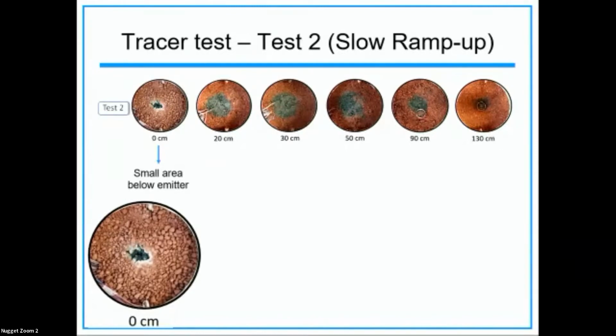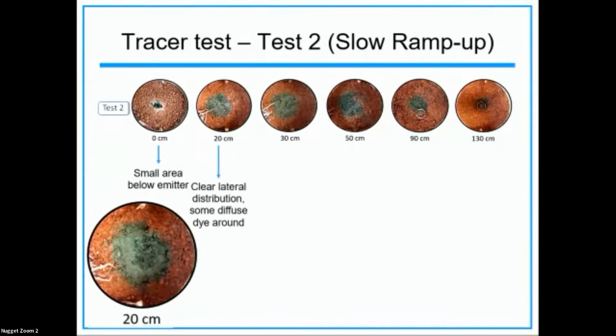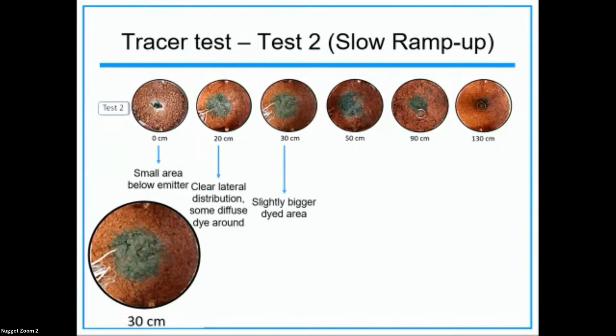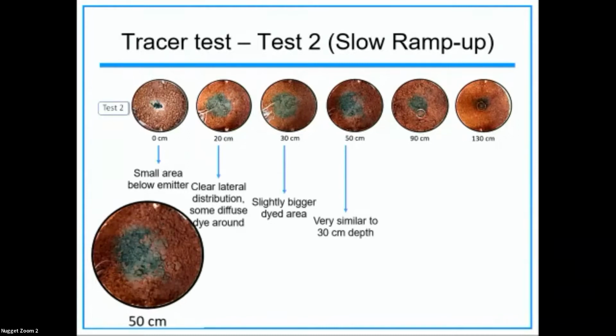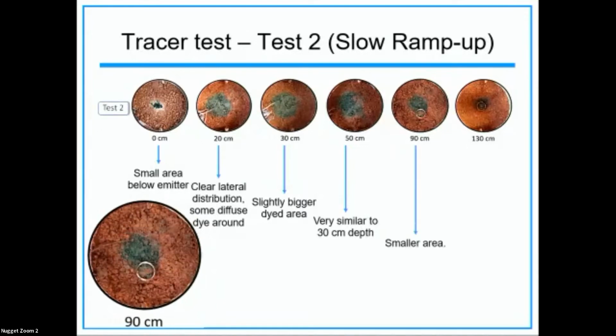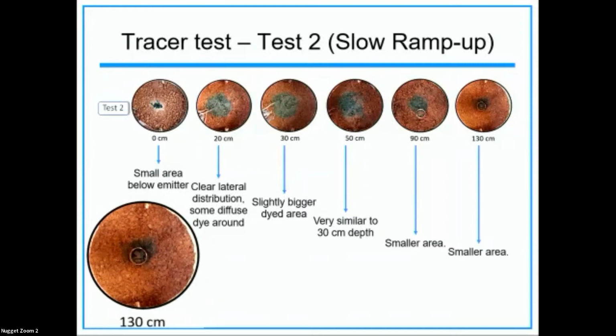But again, this system didn't collapse. So nice lateral distribution, similar to what we saw in the first test. It continues down. And then we're seeing very similar wetting patterns as we do up in the near surface, whereas at 50 centimeters that had disappeared with the fast irrigation. And as we go down, we see that lateral distribution, or at least the dye, diminishing, but it's still below the emitter.